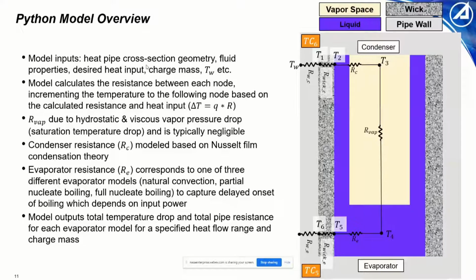And then the evaporator resistance is very interesting. This corresponds to one of 3 different evaporator models. What I mean by that is that for every solution, so for every heat input value, the code is going to march all the way to T4. Then at T4, the solution is going to split into 3 unique solutions. Where those solutions differ is they assume that a different heat transfer process is occurring for the evaporator resistance. So what I mean is that we will assume that either natural convection, partial nucleate boiling, or full nucleate boiling is occurring to calculate the resistance between the T4 and T5 nodes.